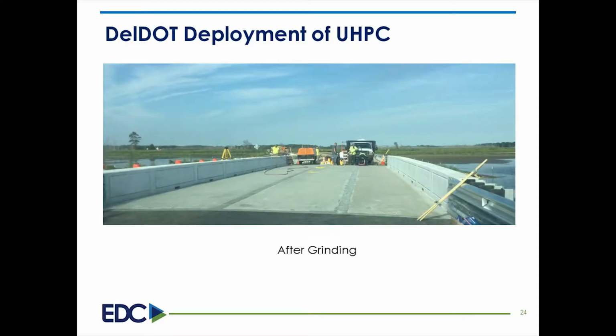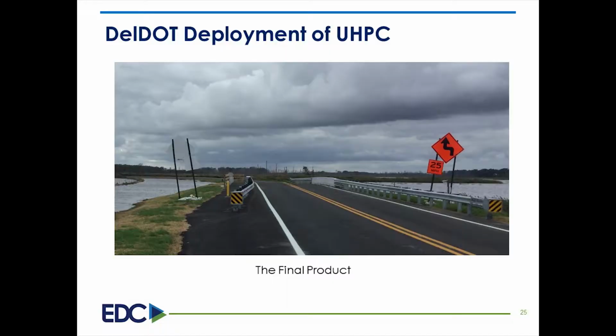because we did not have an overlay on this one. But we had it was a thin epoxy overlay. But this was the final surface after grinding. See, I mean, it came out really good. They UHPC'd it a little bit high, ground down the surface, and then they put what we call a thin epoxy overlay. It's basically the epoxy and then the grit. The final result was really good. You can see the marsh type setting there, but we have a really durable bridge there. So really good experience for us.